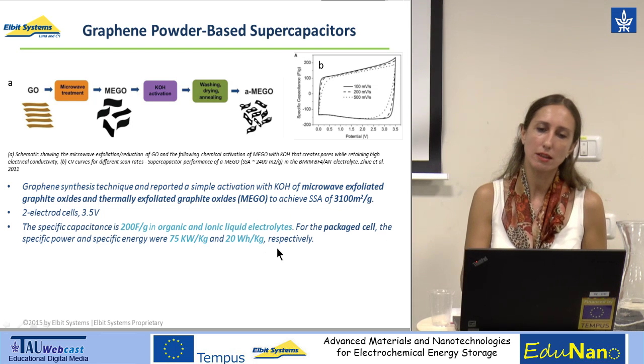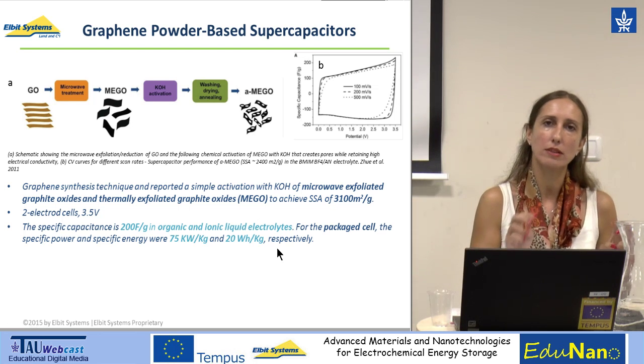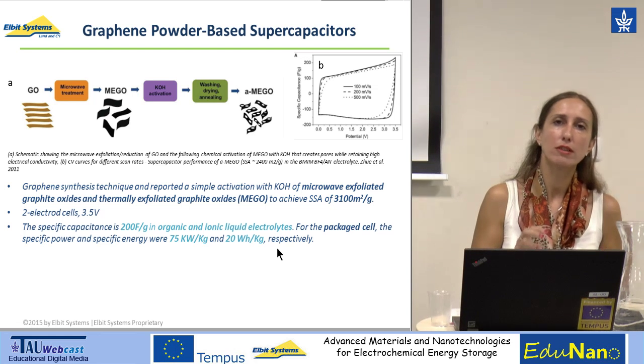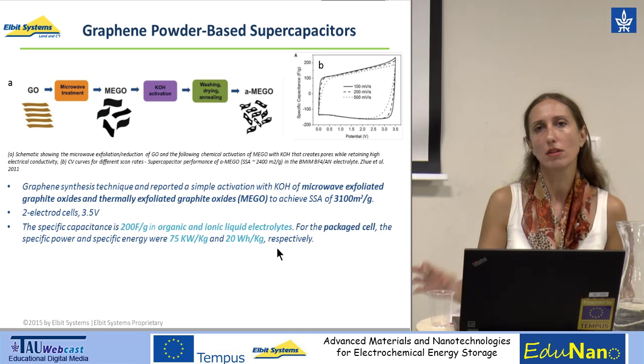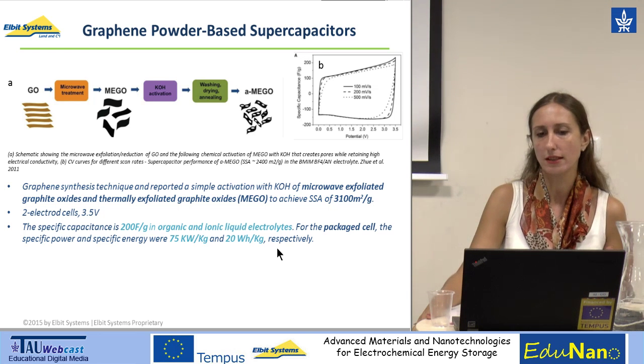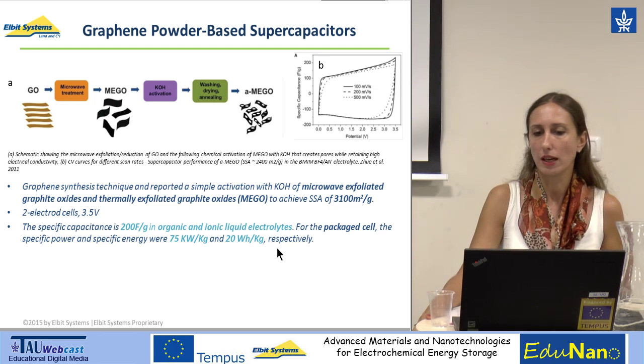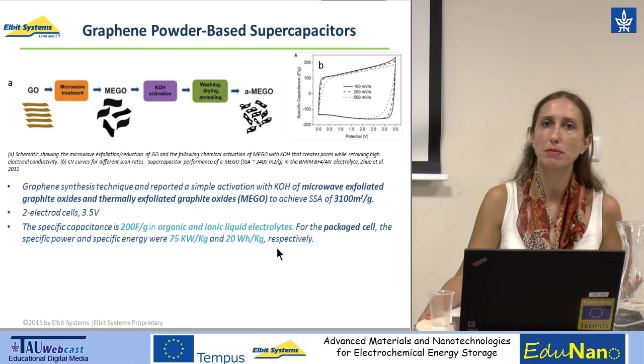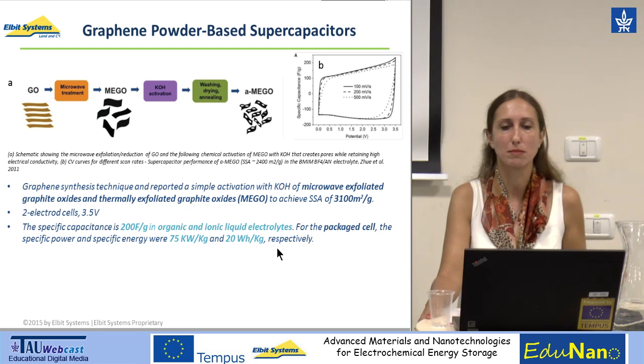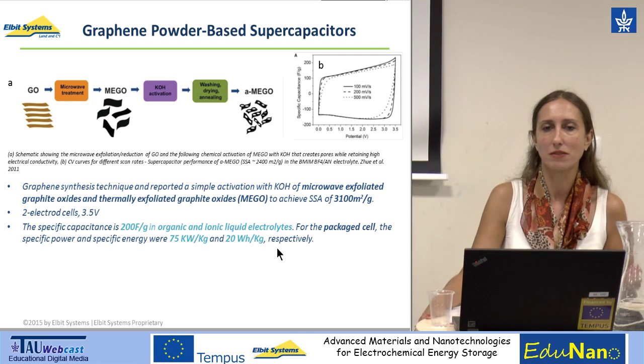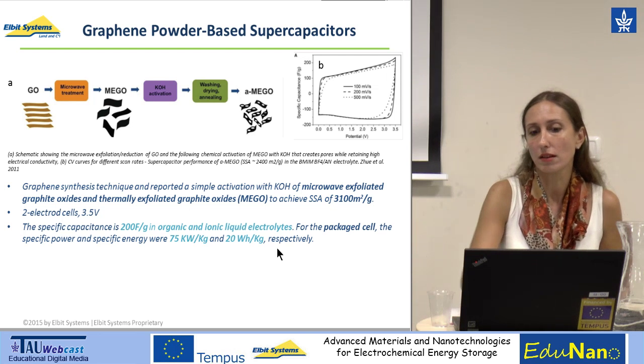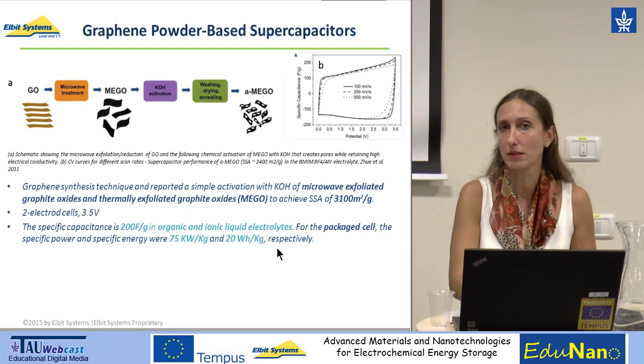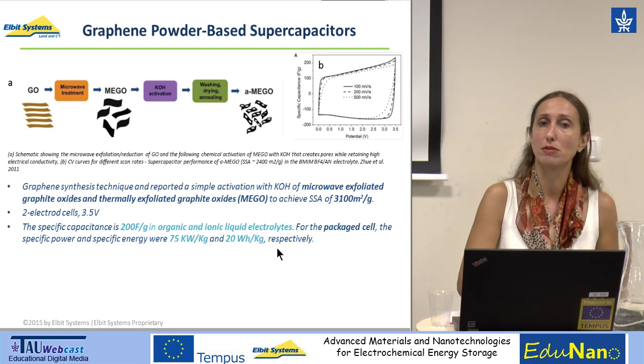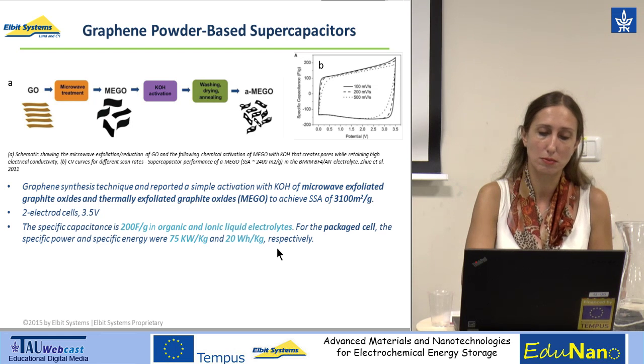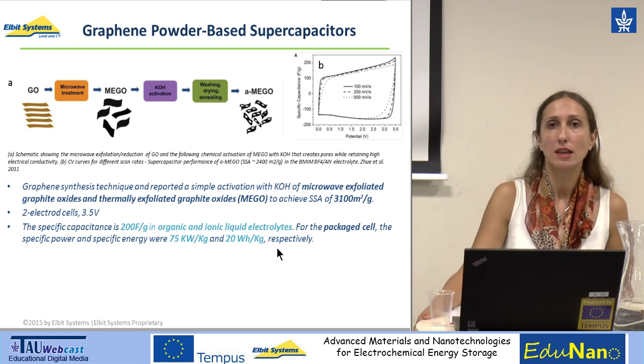So when we are talking about these kinds of values, that they were attained not only for electrode materials per se, but for the overall cell configuration and cell design, then actually it is a very nice achievement. We attained 20 watt hour per kilogram. It puts us much closer to a conventional lead acid battery, and we are talking about a very, very small device over here. And the power density is actually 75 kilowatt per kilogram. It's one order of magnitude higher than the current supercapacitors that are being used today.